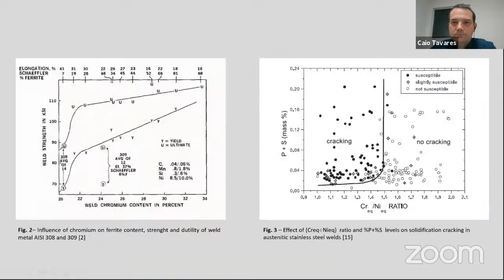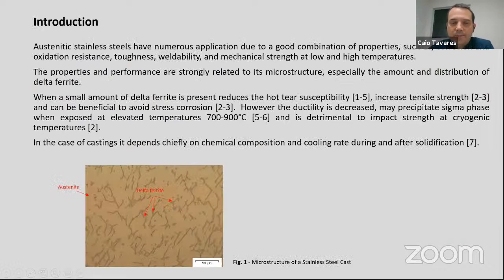Stainless steels have several applications because they have a good combination of properties, especially corrosion resistance, toughness, weldability, and mechanical strength at low and high temperatures. But the properties of stainless steel are most of the time related to the microstructure, especially the amount of delta ferrite. In this picture you see a typical microstructure of austenitic stainless steel. What you see in the background is the austenite, and those darker areas are the delta ferrite.